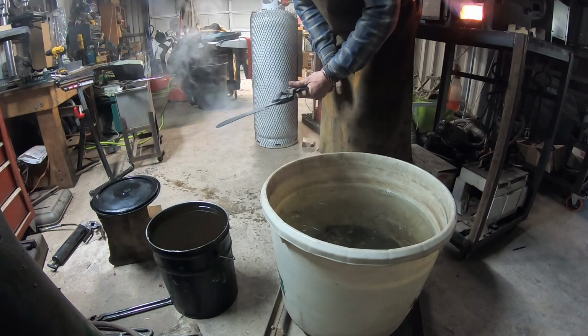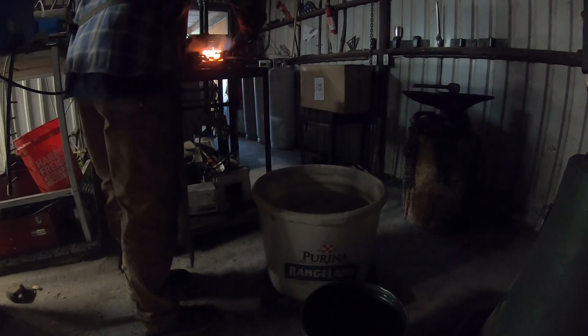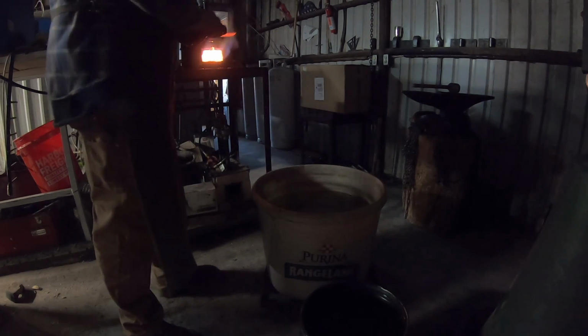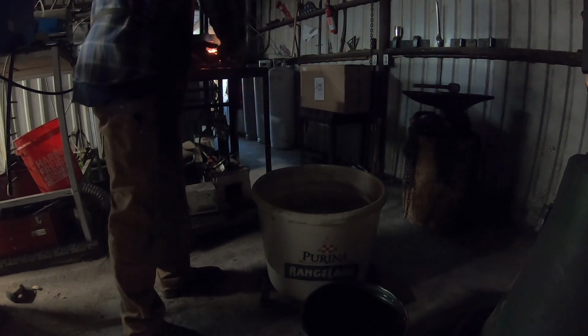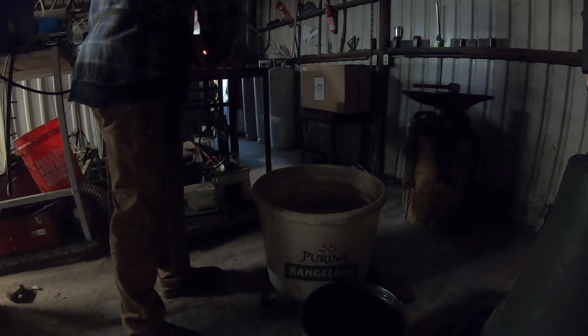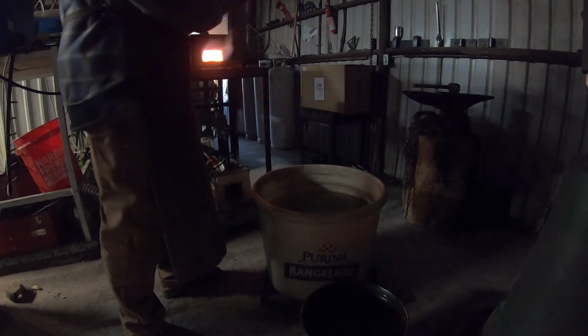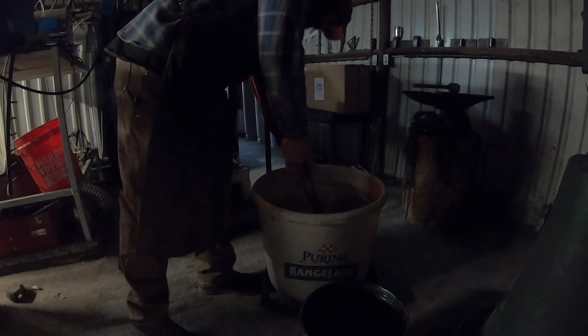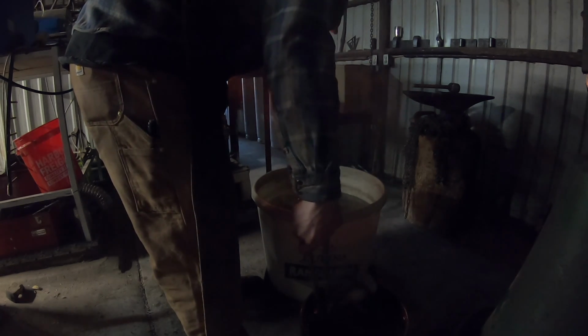Straighten the blade a little bit, heat it back up to an even critical temperature. Again, it looks hotter in the camera than it actually is. And I'm quenching in water. Now, traditionally, you would have a light clay coating on the blade to help even the effect of the quench in the water, which is important because water is not a very even quenchant. But I don't have that, so I'm doing a quick quench in water and then transferring to oil to make sure there's not residual heat that over-tempers the blade.